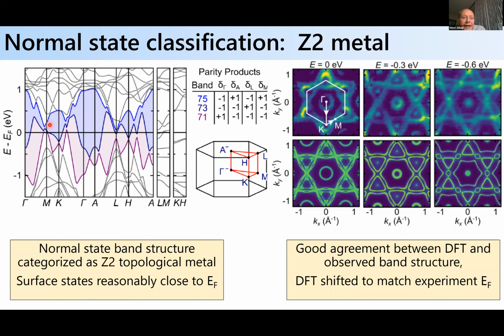And the big difference with this kind of system is that in the cobaltate and in this vanadium compound, you still have the vanadium site. Here it's antimony sites which are in the triangular complementary sites of the kagome. I don't know in the band structure calculation whether you can see the role of these antimony sites.